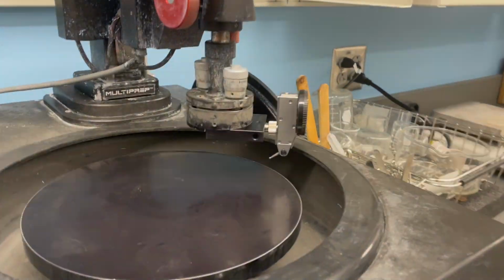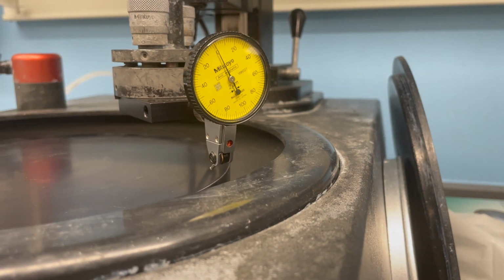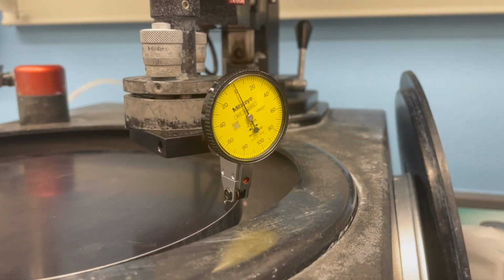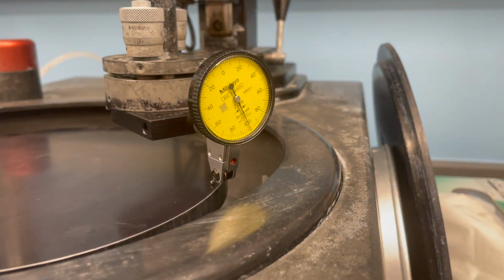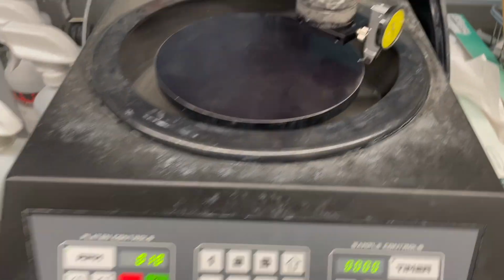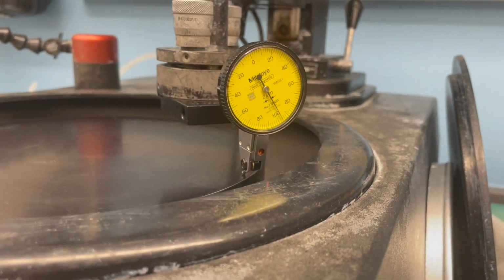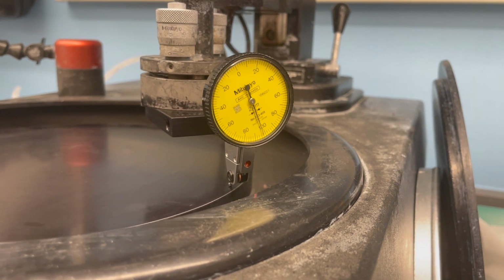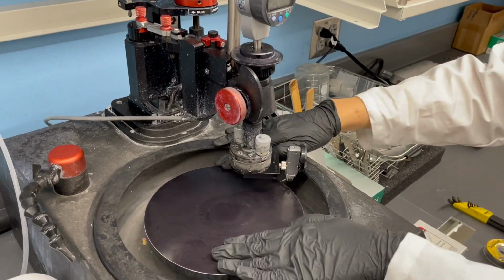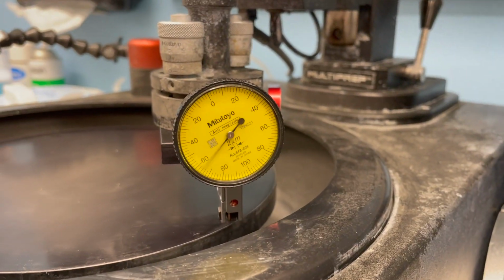Once the dial is on the edge, press the oscillate button to stop the arm, then lower the arm until the dial reads 100. Press the green button to rotate the platen and make sure the dial remains within 2 step sizes of 100. If it deviates too far, raise the arm and wiggle the platen, then repeat the last step.